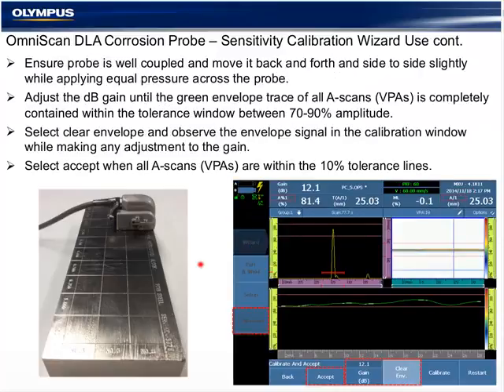So for the sensitivity calibration, a 10% amplitude sensitivity across the probe is the recommended setting, as you step through the wizard, if that is a requirement of your work procedure. When you're looking at the trace envelope in the sensitivity setting, again, we see the focal law 1 or A-scan 1 from this side of the probe. This is the middle of the probe and the far side of the probe.